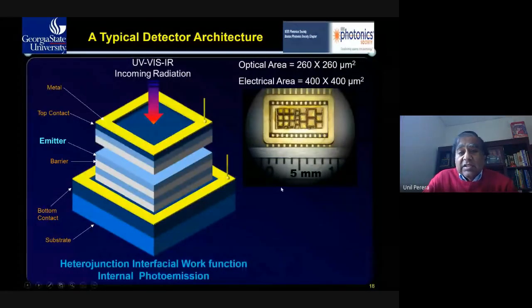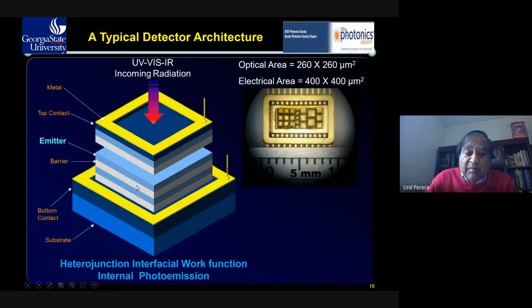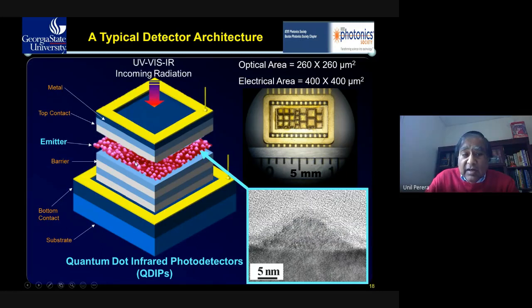And this is just a typical detector architecture. We start with the substrate. You have a bottom contact and layers, emitters and barrier layers, and a top contact and a metal. The contact region is highly doped because otherwise you cannot get a good ohmic contact. So the light comes through here, and these are different types of emitters. So you can have quantum wells, dots, other heterojunctions, any other type of emitter, and the same structure can work. And we have used this similar structure for all of our devices.